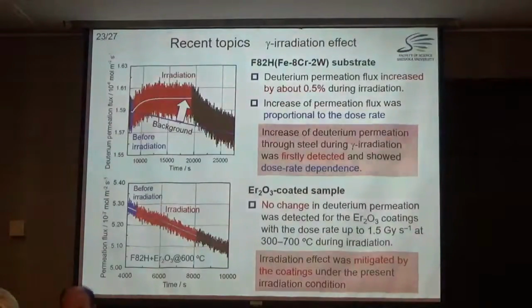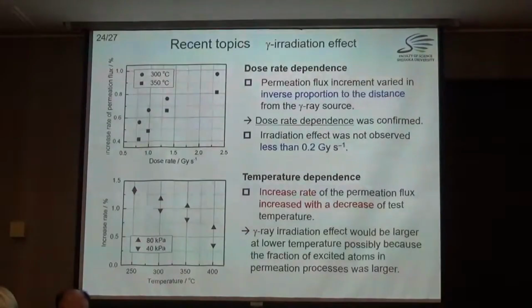However, in the case of the erbium oxide coated sample, there is no decrease of the permeation, no change. So the erbium oxide coating mitigated the irradiation effect under the present irradiation condition. But in the case of a fusion reactor, it is a really high dose rate gamma ray, so in this case we don't know. Nobody knows the situation. This is the dose rate dependence and the temperature dependence. At high temperature, the increased rate decreases, so we care about the lower temperature, where a high increased rate of the permeation flux was detected.